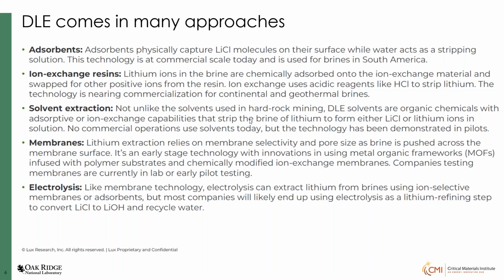The ion exchange resins are the other kind, such as lithium titanates or manganese oxide. The way it's done is exchange: you exchange lithium with the proton ions from the resin, and then you have to use acid, hydrochloric acid, to delithiate and strip the lithium. This technology is again nearing commercialization for both continental and geothermal brines.